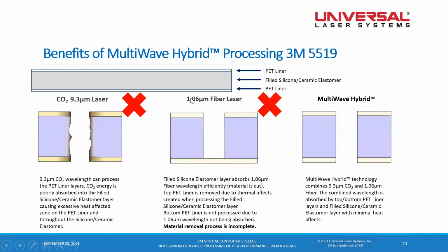So by combining 9.3 and 1.06 together in MultiWave configuration, you can see that we were able to cleanly cut all 3 layers at an acceptable level. So by using traditional laser technology, we could not produce an acceptable part. And now by using MultiWave hybrid, we can accomplish the goal. So for 3M and Universal Laser Systems, we looked at this as a significant win and a good reason to help move this material forward in the market.